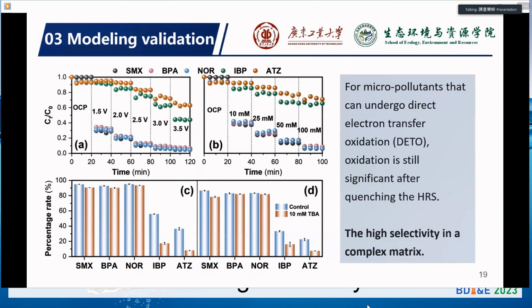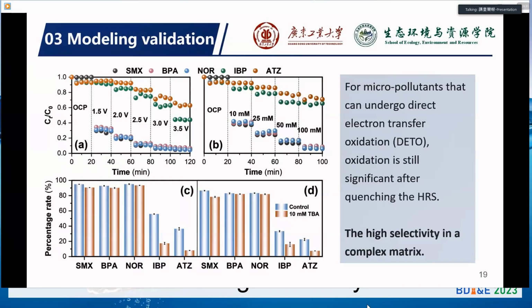We further justified our results from the modeling and visualization parts by oxidizing a few kinds of micropollutants in the IEM system. We found that scavenging at the top layer, which can generate hydroxyl radicals, had minimum effects on the oxidation rate of the electron-rich micropollutants, SMX, BPA, and NOR. But for the refractory species such as IBP and ATZ, the oxidation rate was significantly affected.